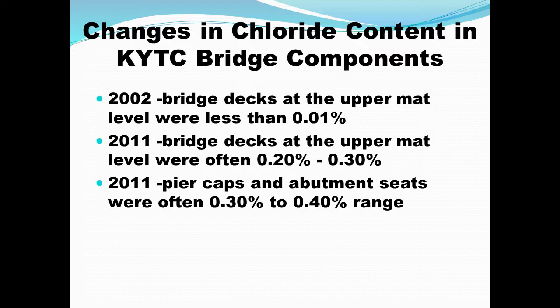In the same geographic area, we looked at more like 40 bridges, and we looked at not only the bridge decks, but the substructures and the pier caps and abutment seats. What we found was that in 9 years, we had gone from negligible amounts of chloride at the upper mat level to 0.2 to 0.3% in many cases in the decks, and 0.3 to 0.4% in many cases on pier caps and abutment seats. Obviously, a lot of chlorides had intruded into the concrete in that 10-year period.